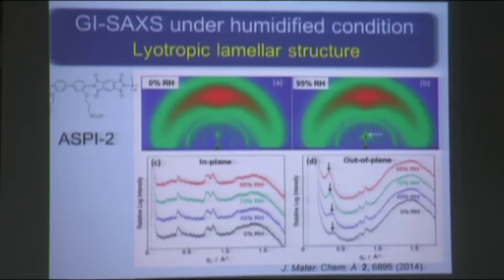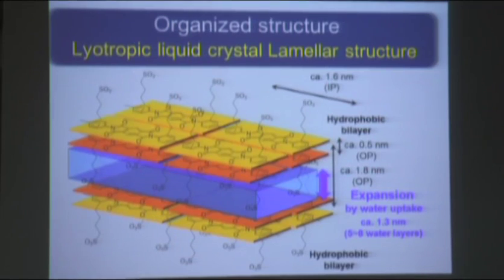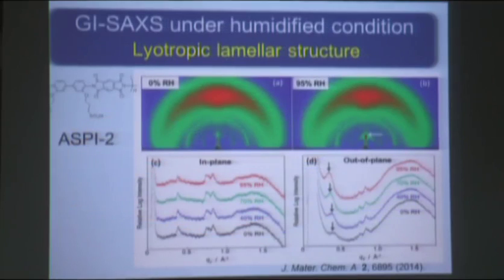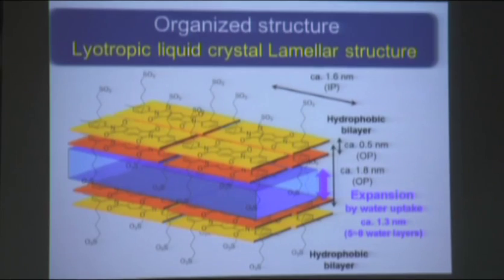So you see the black and red, from 0% humidity, dry, to the increased humidity, the red one. But the in plane diffraction does not change. But in the out of plane case, it is different. From the dry to the red one, you see that this peak is moving to the lower value. So this means totally anisotropic structures. By analyzing this, we can see the lyotropic lamellar structure based upon the liquid crystal properties. So here is again shown the organized structure. You see this is in plane, 1.6 nanometer. This corresponds to the unchanged peak here. This is polyimide, so please don't look at this. And this peak corresponds to this direction.